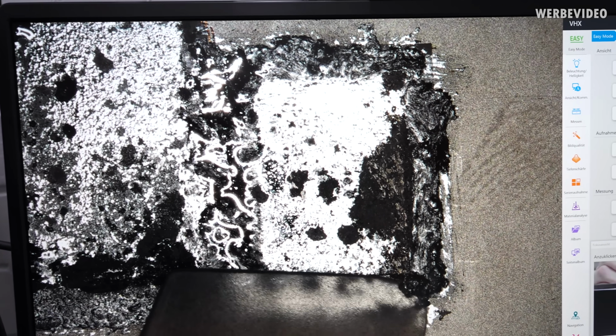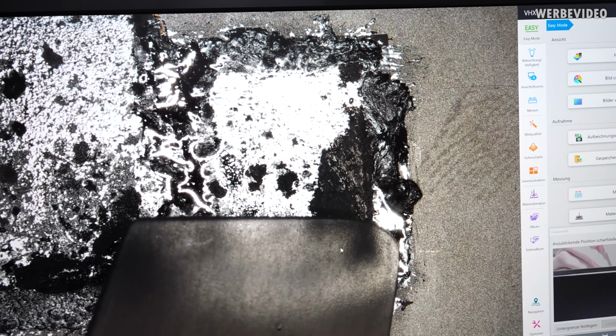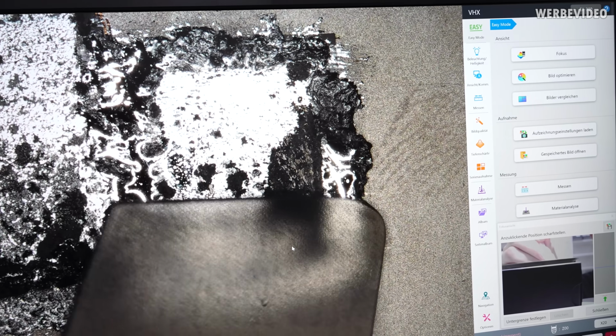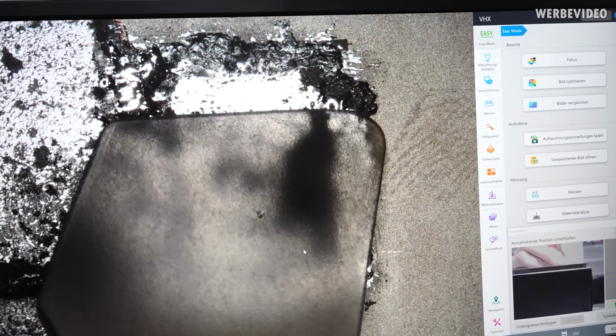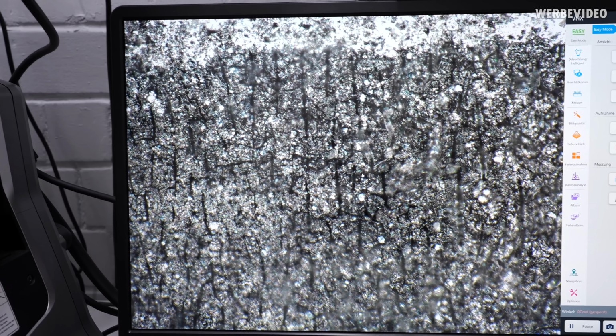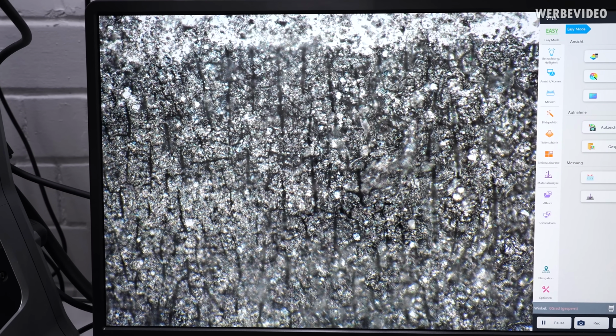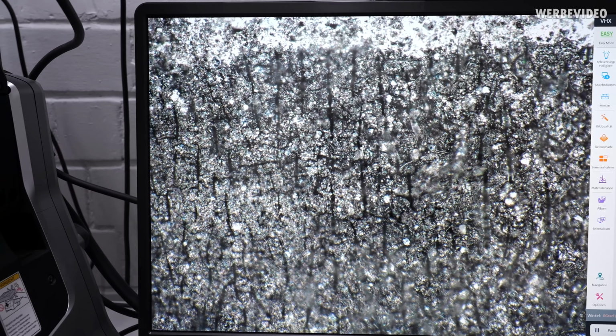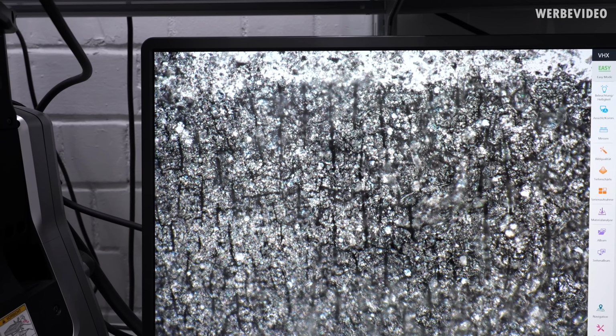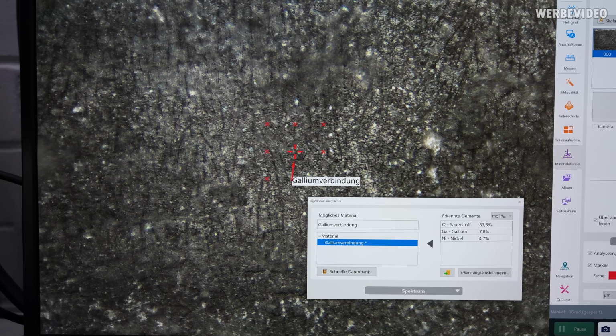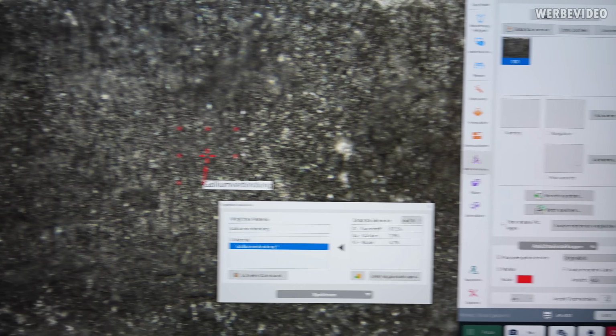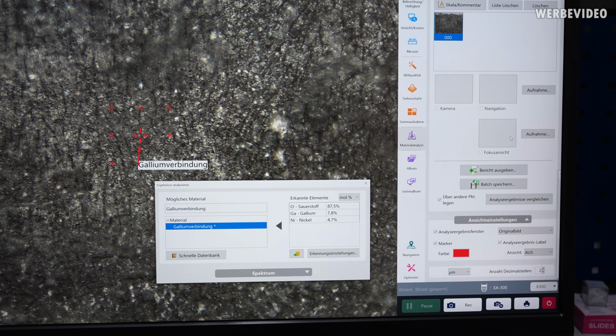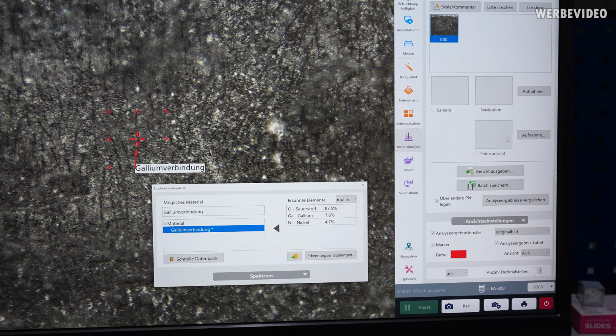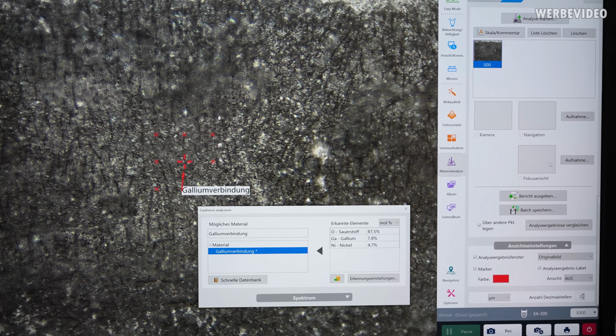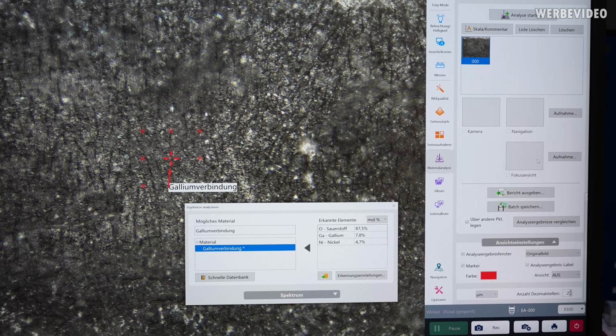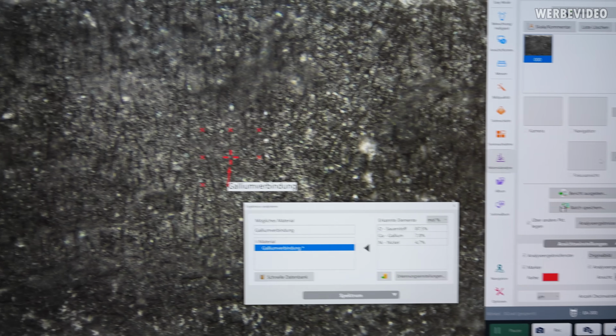The black stuff I'm removing here is probably just a lot of oxide on top of the liquid metal. Quite interesting though, if we zoom in 500 times magnified onto the black area, there are like cracks in the surface, which is very interesting. I quickly also performed a material analysis, and you can see it's about 5% nickel, 8% gallium, and about 88% oxygen. So it's definitely, as we expected with this black stuff, gallium oxide, with a little bit of nickel probably from the heat spreader underneath.